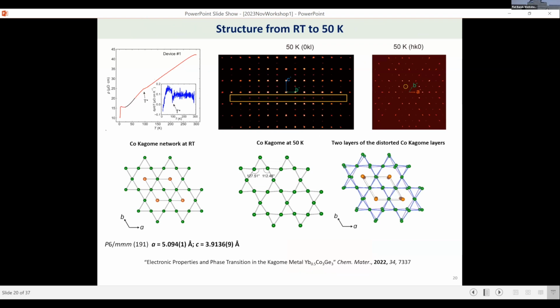So the most intriguing part about this particular 166 or half 33 compound is that, unlike the other 166 phases, the cobalt atoms are actually not puckered up. In fact, all you see is the twisting. That's unique. It's not up and down, but rather sideways. Another thing that is really neat is that the cobalt distances do not change. So it's actually quite rigid. The only thing that changes is the angles, but the distances are not changing.